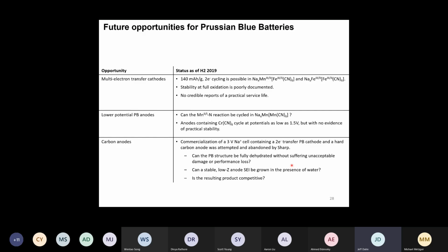Now, if you look at this stuff, and if you take the compound in the middle set of rows, which is easy to look at, you have 1 sodium that's going to go in and out, 1 manganese involved in the redox, and then you have, count them, 13 junk atoms. 13. So this stuff is going to have a terrible volumetric capacity and hence a terrible volumetric energy density, just with simple rules like that.